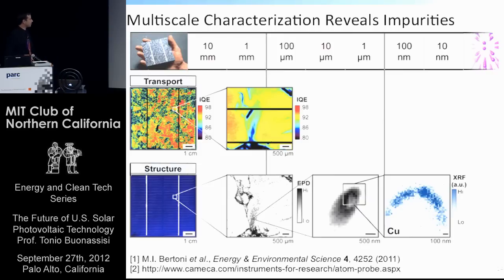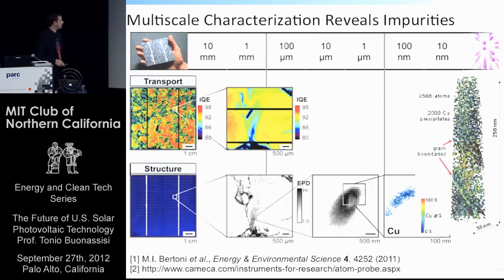We can do even better. We can create a small little tip of our sample, and one atom at a time, run it through a mass spec onto a two-dimension position analyzer and obtain a map, a 3D map of reconstruction of the distribution of atoms within the sample.